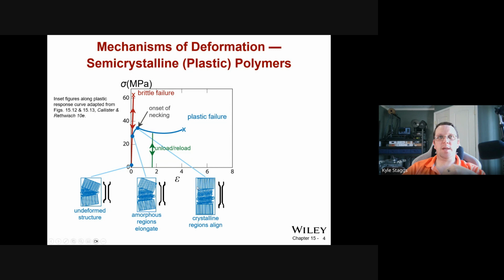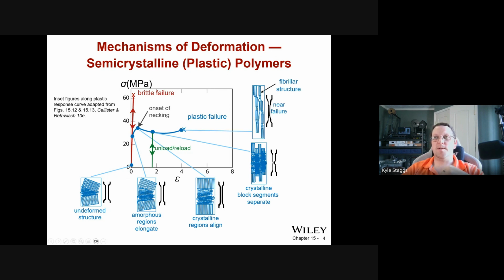Once you reach this peak, whatever the ultimate tensile strength is for the material, that's where the majority of the chains have aligned, and you've reached a point where they can't take any more abuse, but they do change dramatically in terms of the strain that's absorbed at that given stress level. The stress level drops just a little bit as the area changes. You start getting this necking phenomenon at this point. You begin to get block segments ripping and tearing and separating. This is the beginning of the failure, and then you get a fibrillar structure. Individual fibrous strands are what you end up with near the actual failure point before it finally detaches, where one of those threads gets thin.